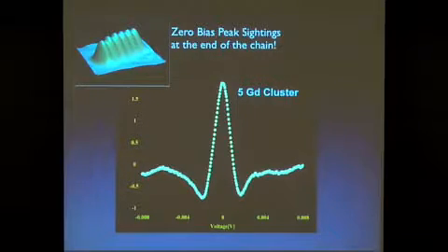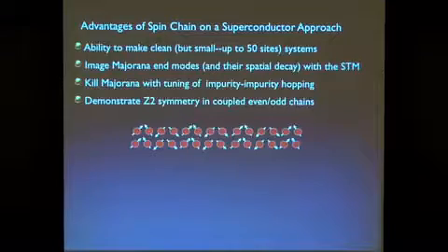Right. So that's what I mean. The spin texture is... so it turns out. Okay. So the idea is this, and you can find this in the calculation. You need some finite angle between the spins, and you can think of this in the following way. What we are trying to make is a p-wave pairing, nearest neighbor pairing. So imagine you're a pair of electrons. You're trying to hop into two nearest neighbor sites.